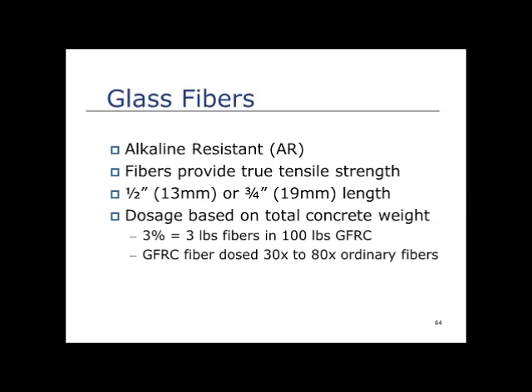Longer fibers give you more strength than shorter fibers, but shorter fibers sometimes are more appropriate for very small, intricate pieces where you're not making a very thick casting, but it's got a lot of intricate detail and you have to go around a lot of corners. So sometimes half-inch fibers are good for small pieces, but generally 3/4 inch is the preferred fiber. And the dosage is always done the same way, based on the weight of fibers versus the weight of, in this case, the GFRC.